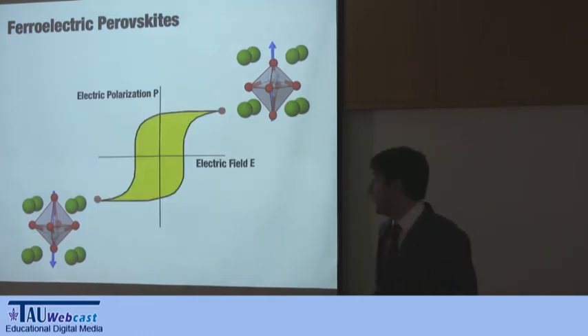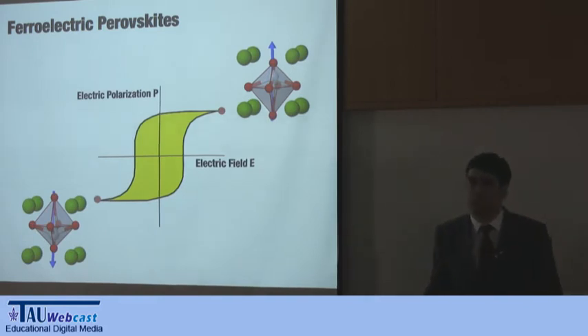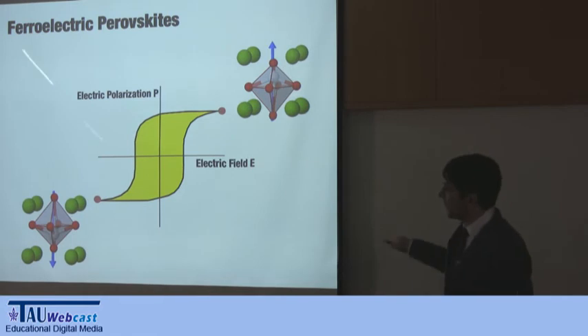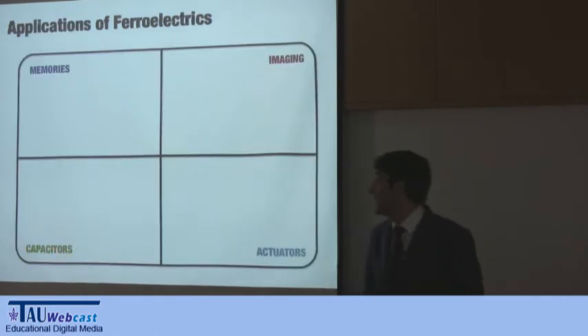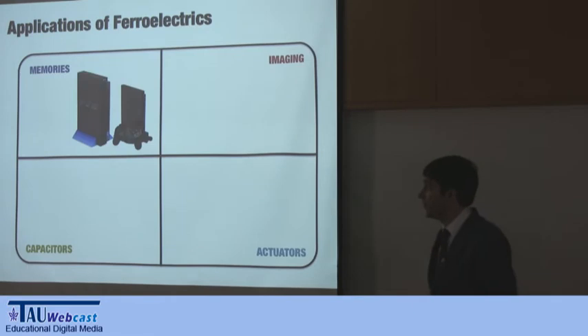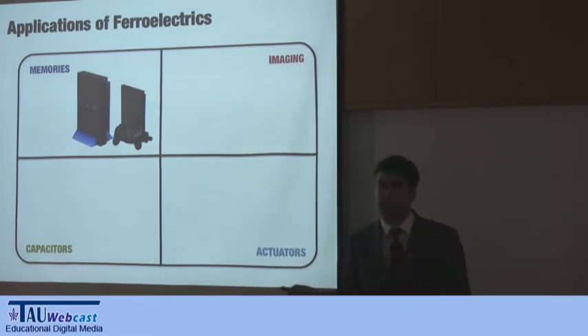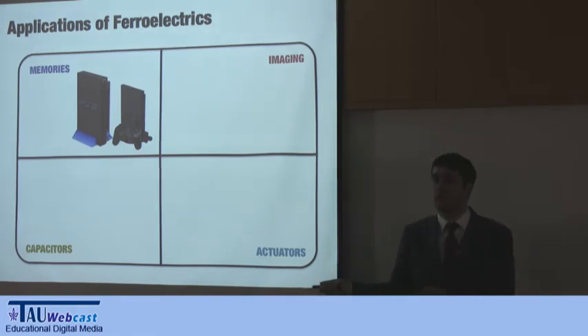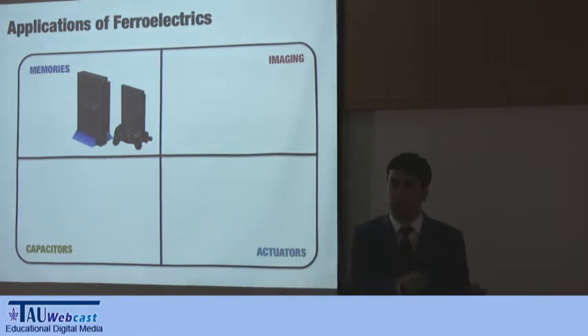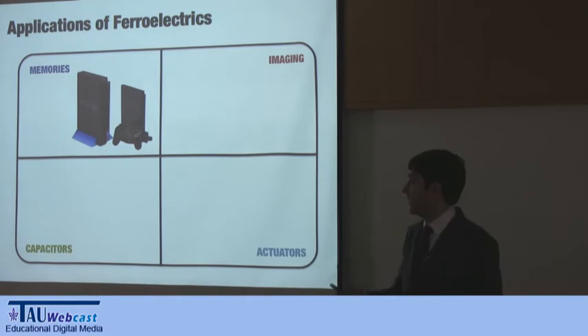To be a ferroelectric, a polar material has to be switchable. So if you apply a field in this direction, you have a hysteresis loop, and you go to the other phase. Okay, so you can switch the polarization between the two, and this has technological applications. For example, in memories, this is the PlayStation 2 that includes ferroelectric memories. Because you have two directions of the polarization, you can encode ones in one of the directions and zeros in the other direction, and this will stay. So this is memory that doesn't change when you unplug your computer, and is used.